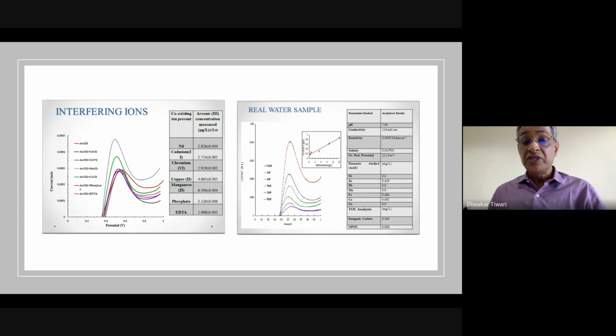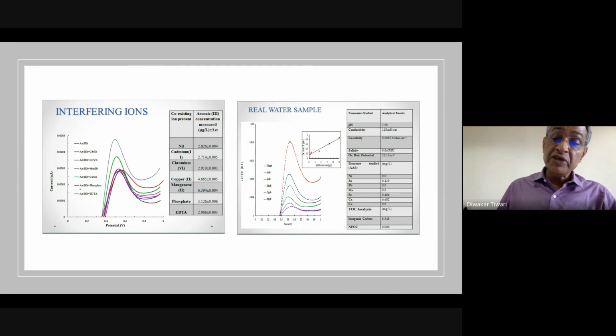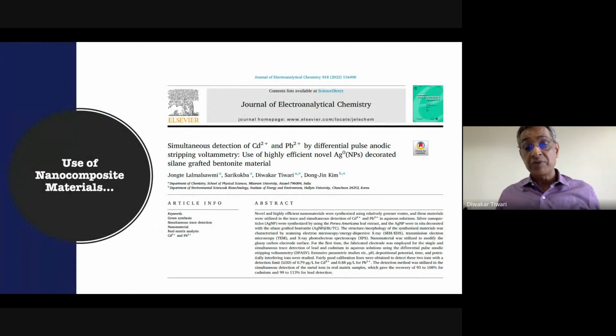And these are some interference and real water analyses that we have done. We collected some water from the river and analyzed it, and after that we spiked it with a known concentration of arsenic, and we could get a very good straight line and all that. Even then, the LOD value was also very low, comparable to that.